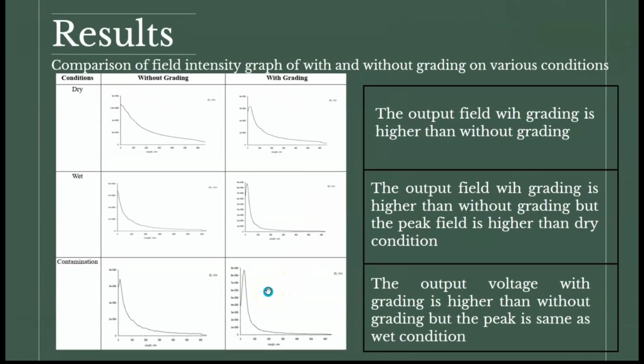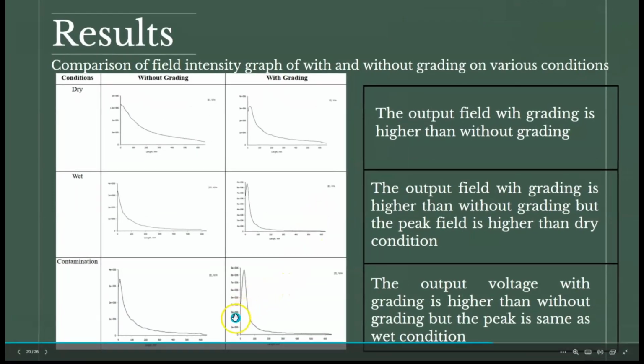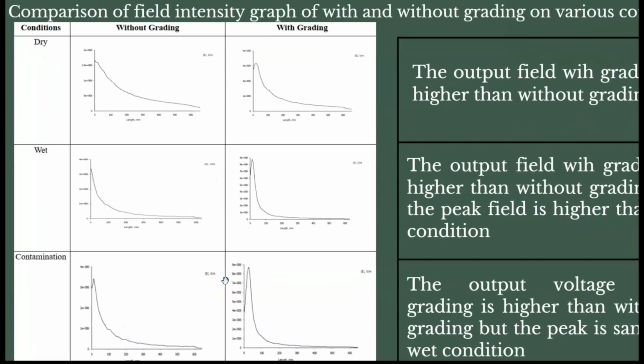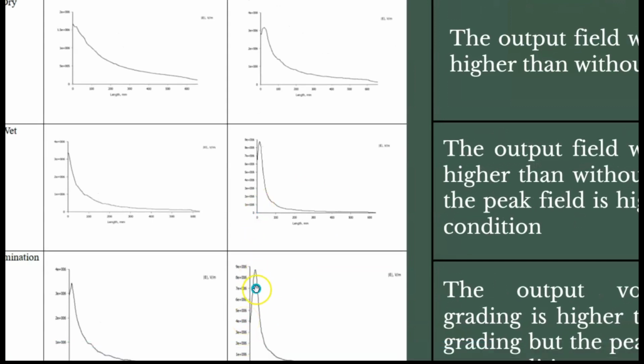And the last one is the contamination condition. The output field with grading is much higher than without grading, but the peak is the same as the wet condition. But as we can compare between the wet and contamination conditions, the contamination condition is much steeper in increasing the intensity than the wet condition.